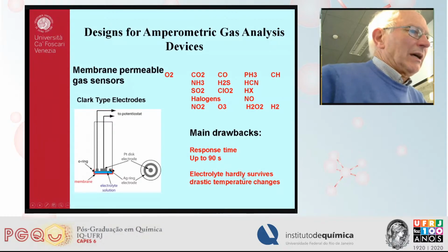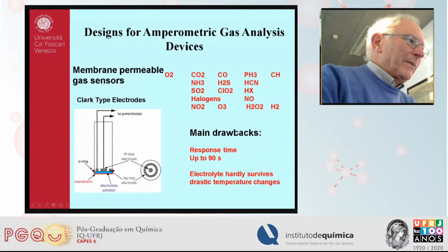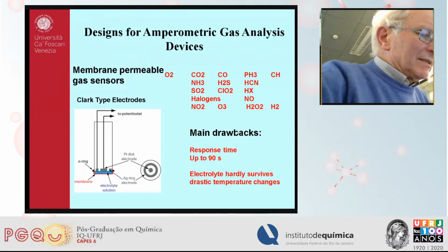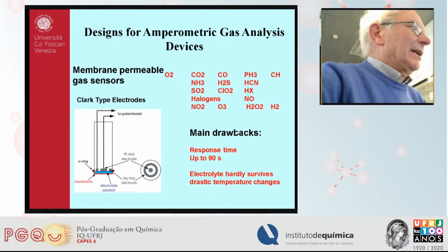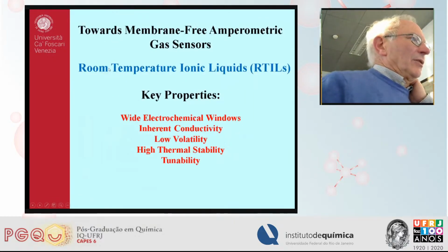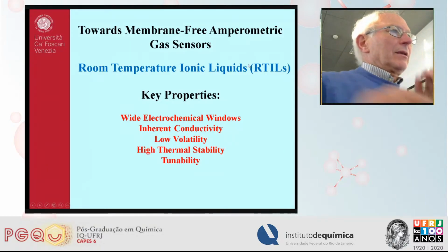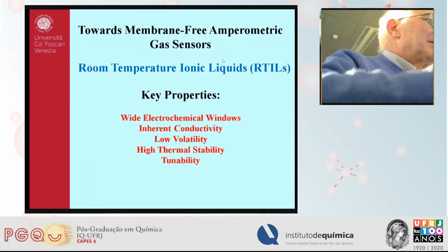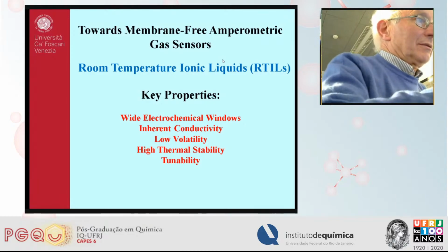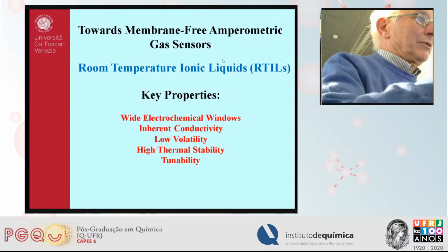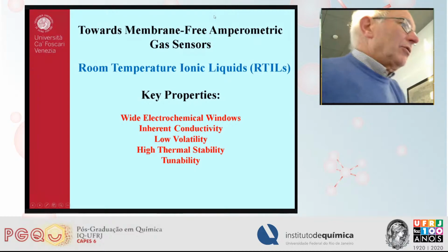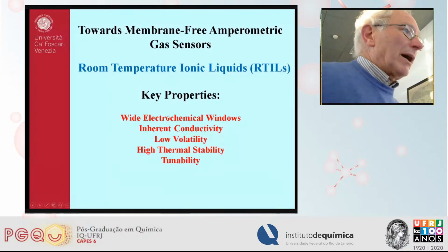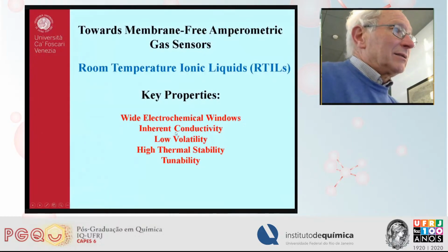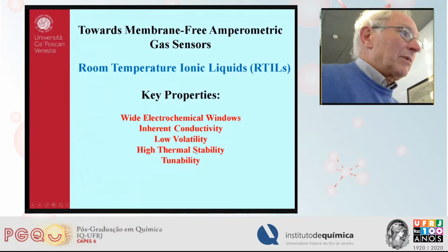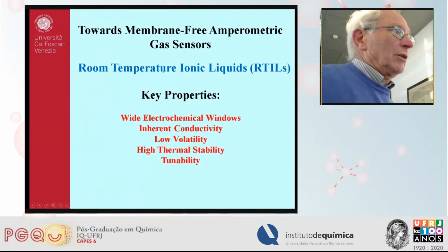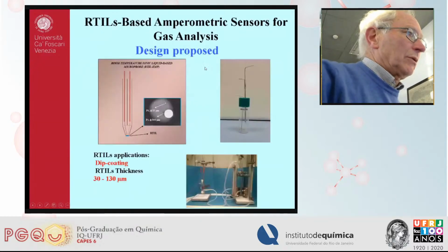The electrolyte inside the medium hardly survives changes in temperature. Okay, so we try to prepare a miniaturized electrochemical cell for gas analysis by using room temperature ionic liquids, okay, as solvent, which can be applied directly on the electrodes, on 2 or 3 electrode systems. Why ionic liquids? Ionic liquids have very good properties. They have a wide electrochemical window, high inherent conductivity, low volatility, high thermal stability, and also tunability by changing either the cation or the anion of the room temperature ionic liquids.